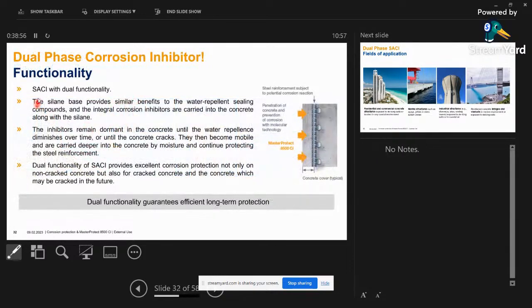So as we say, it is a dual function. The silane provides the benefit of water repellency because it basically makes the concrete surface hydrophobic in nature. So as a result, the concrete's water repellency goes up. And then you have got the corrosion inhibitors. The integral corrosion inhibitor, which is part of this molecule, is a chemical added to this formulation, which basically allows the passivation of the steel reinforcement in the concrete along with the silane. So that's the dual function with which it works.